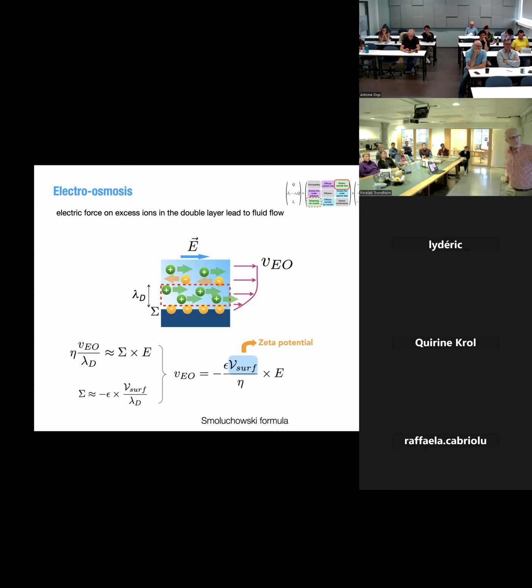This force will induce a shear flow, a shear stress. This shear stress is nothing but the viscous shear stress, so viscosity times the velocity you will acquire divided by the Debye length, over which you have a gradient. And this is balanced by qE, I mean, charge times E. At the same time, the charge is proportional to the zeta potential, which is the surface potential. So if you balance the two, you get immediately the Smoluchowski formula. That's quite standard and it works very well.